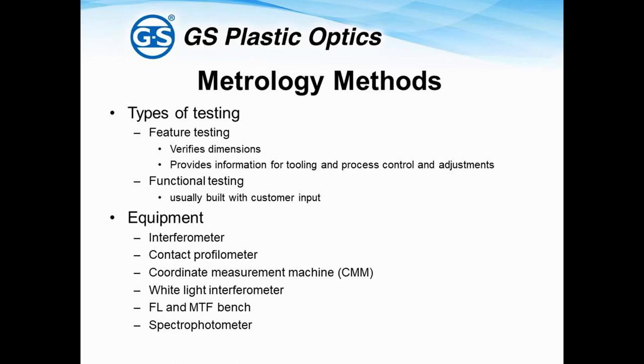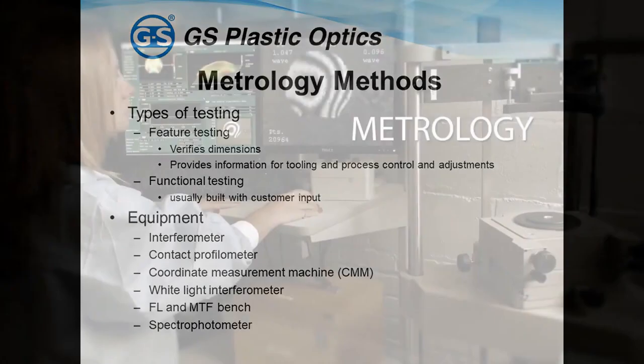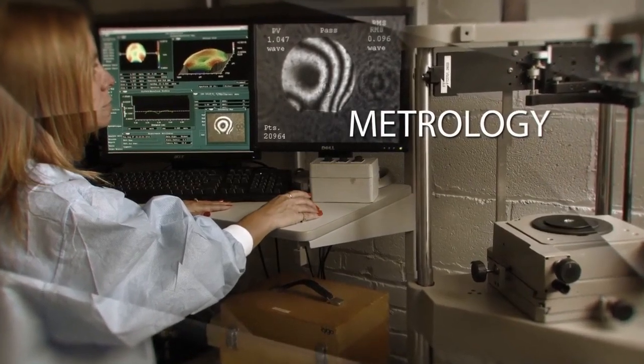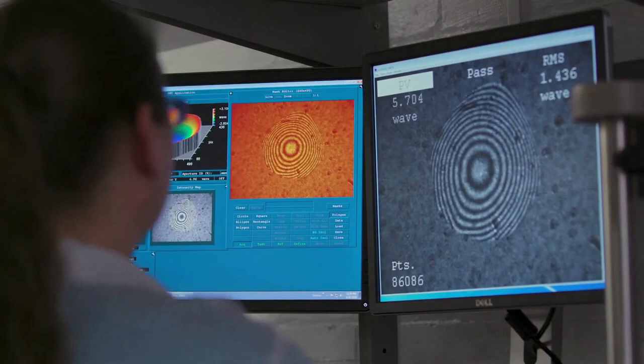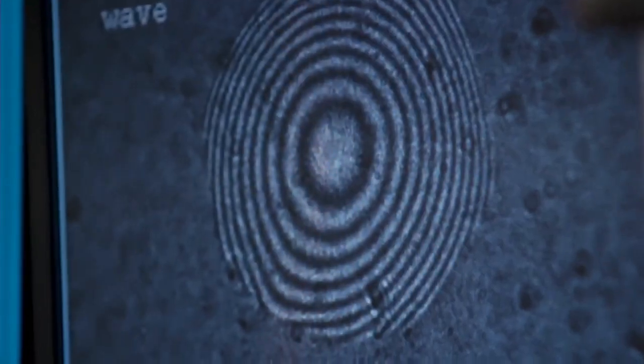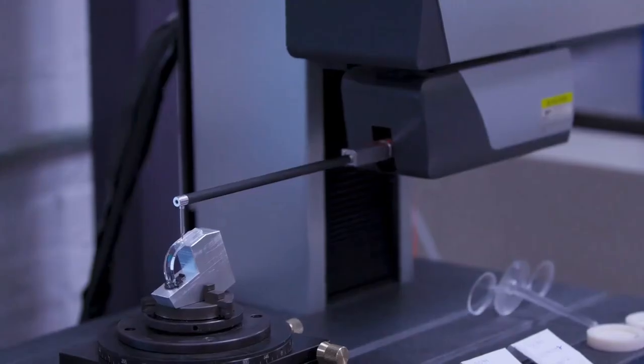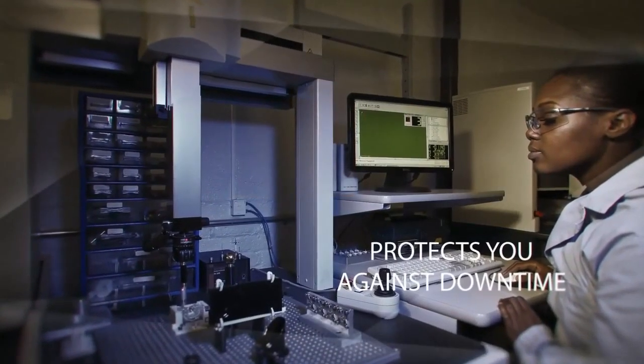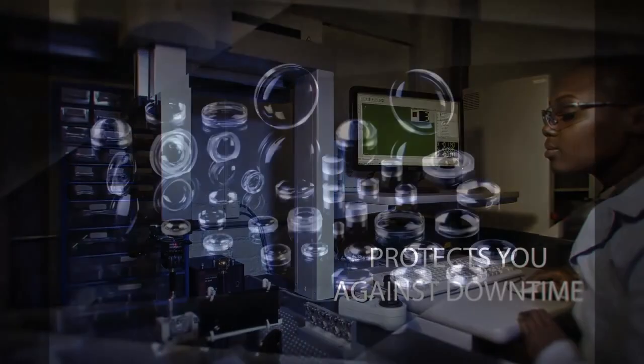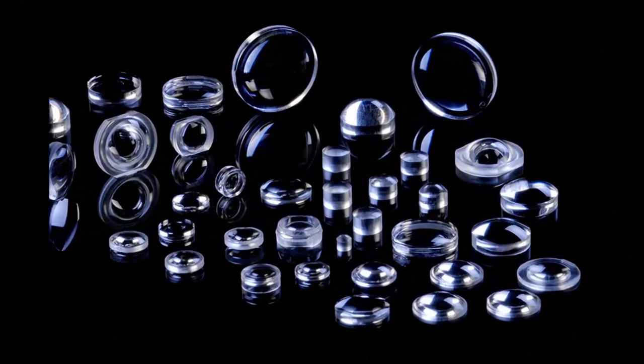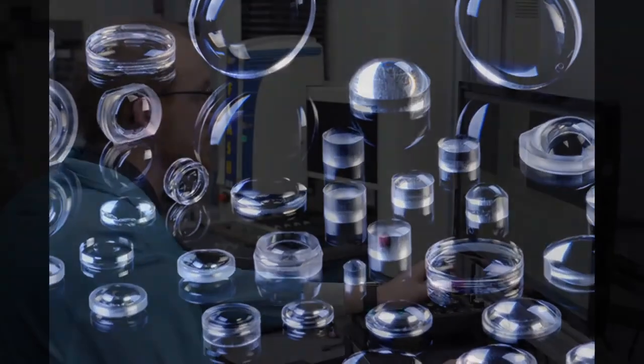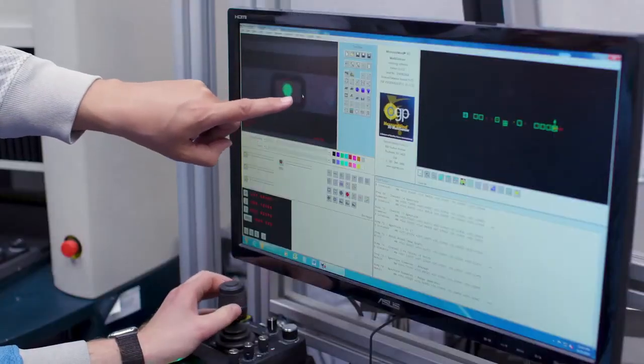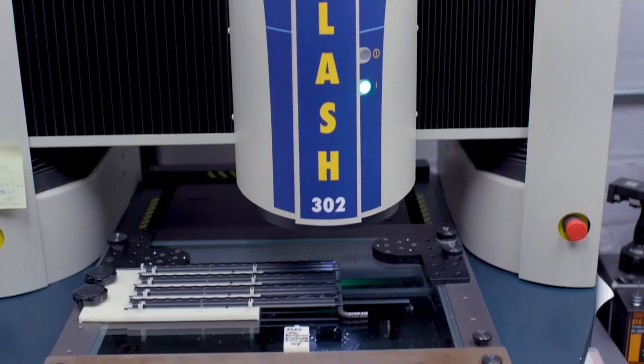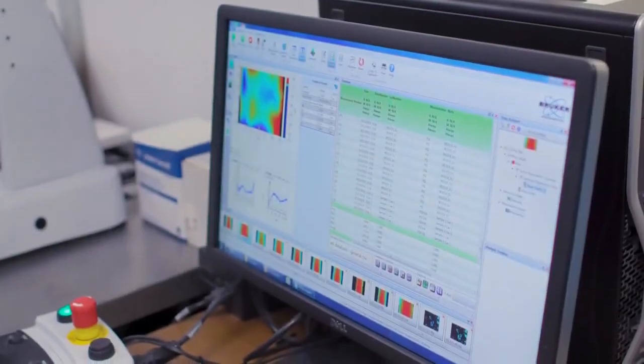Having good metrology is an absolute requirement when molding optics. Most optical surfaces can be tested on an interferometer. If the surface is aspheric, null correctors can be designed and employed. Another useful device is a contact profilometer, which can be used to trace aspheric surfaces and measure form errors. Because of the common practice of integrating mechanical and optical features into one platform, appropriate metrology is required to assure these features are to print. A coordinate measurement machine is useful for this application. This is especially true if the molded optic has optics in multiple planes relative to a datum.